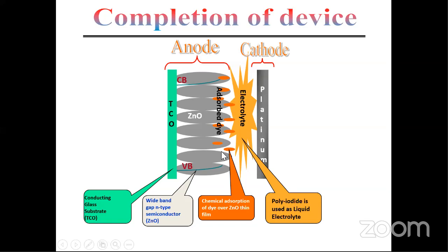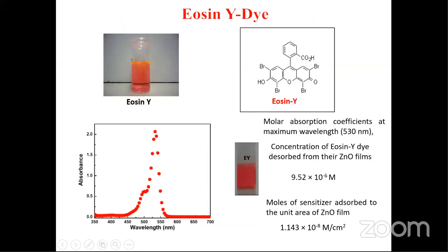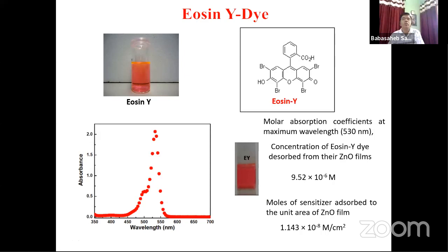Initially we have used eosin Y as a dye to adsorb on the zinc oxide, which is red in color. But eosin Y has very low absorption in the visible part of the solar spectrum. You can see that it has absorption against wavelengths of 500 to 550 nanometers, which means very low absorption in the visible part of the solar spectrum.